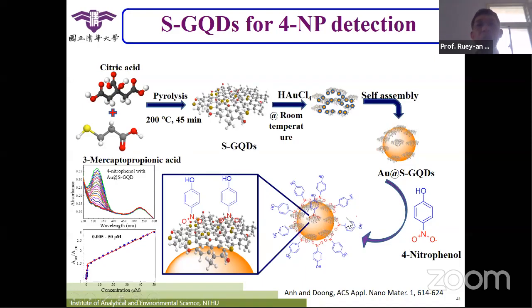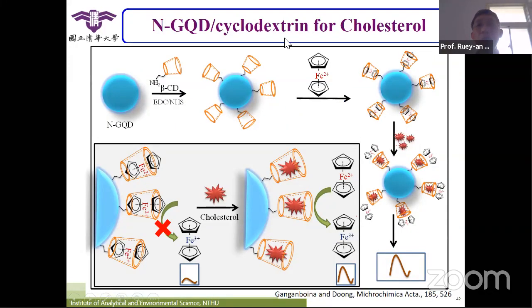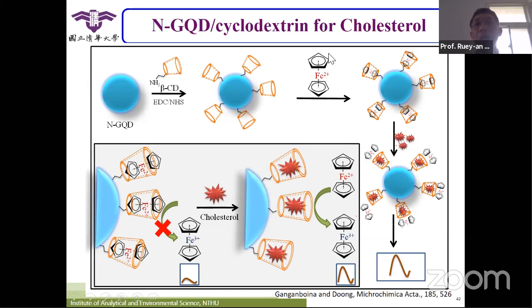We published this two years ago. You can also use the GQDs with beta cyclodextrin to detect cholesterol. So here is the case. You use a GQD with beta cyclodextrin on the surface, and if you have ferricyanide, it can be here. If you have cholesterol, it can get inside the cyclodextrin and replace the ferricyanide. So the peaks, the electrochemical properties, change dramatically. From these electrochemical properties, we can detect the cholesterol quite easily.